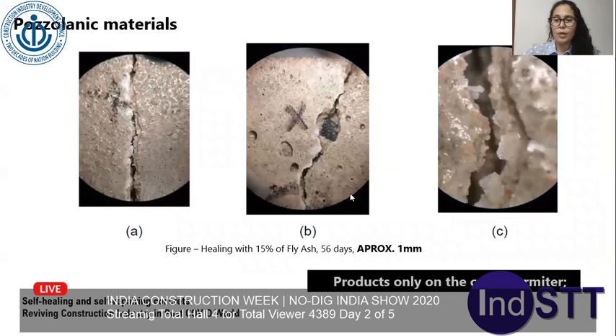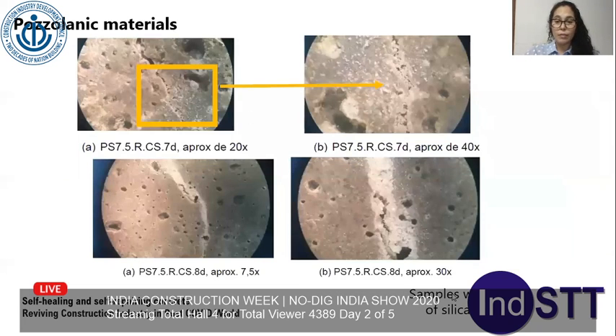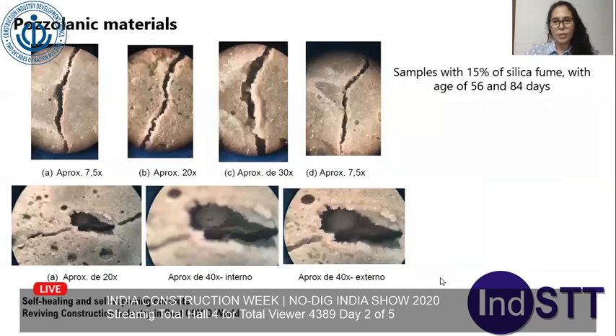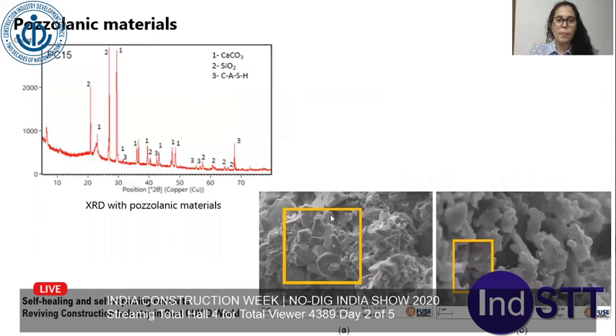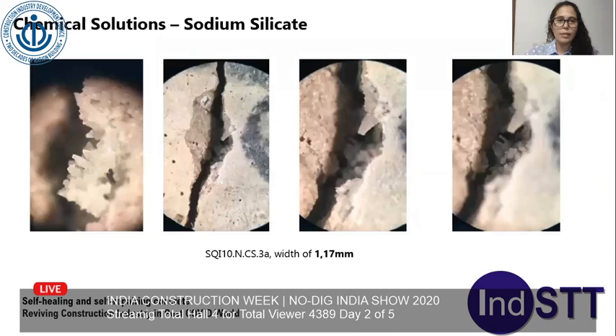With pozzolanic materials, we checked that the product was mainly formed only on the cracking perimeter, with a width of usually 1 millimeter. We have samples with 7.5% of silica fume and 15% of silica fume replacing cement, and we also check the crystals that are forming on the crack perimeter. And we see almost the same materials as in the other mechanism, and we have those products as layers from the same analysis.